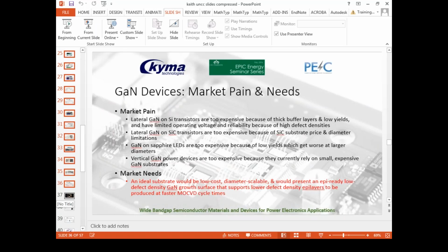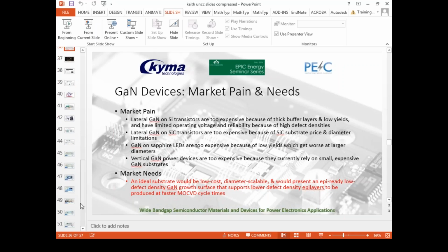So this is one of, I think, 3 focus slides on, I showed you the gallium nitride substrate prediction that I put out there in 2009, where you'd end up with this smart cut of gallium nitride on something that was cheap and behaved well otherwise. So we had in May of 2015, not too long ago, a group come to us and say, hey, we've got this highly engineered substrate, and it's got GaN on the top, but we'd like you to make that thicker by HVPE and see what you think. And in retrospect, well, it's turned out really well. So we're adopting this deck of slides.